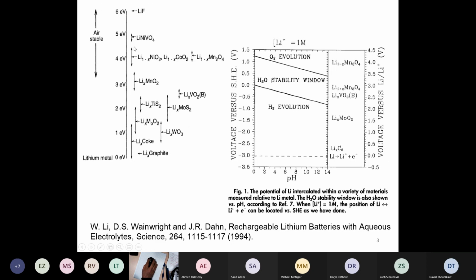You have to figure out where the common lithium-ion battery electrode materials, shown over here on the left, line up relative to the stability window of water. Water will evolve hydrogen if the potential is too low, and it will evolve oxygen if the potential is too high. This chart shows where the common lithium-ion battery materials lie relative to the water stability window for a 1 molar Li+ aqueous solution. It's also dependent on pH, so you can adjust the pH with counter ions.